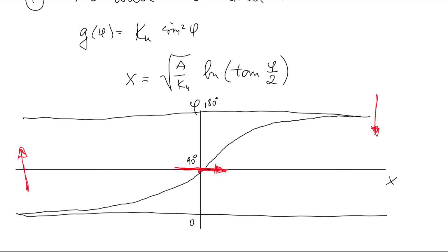Now formally, if you look at this function, you will see that this is formally an infinite wall because it approaches 0. There is no certain place where it would be absolute 0 or absolute 180 degrees. It approaches this value. So in order to measure the domain wall thickness, what we do is the following. We look at the slope in the middle and we draw a line with this slope. And it's not the best color. Let me duplicate it.